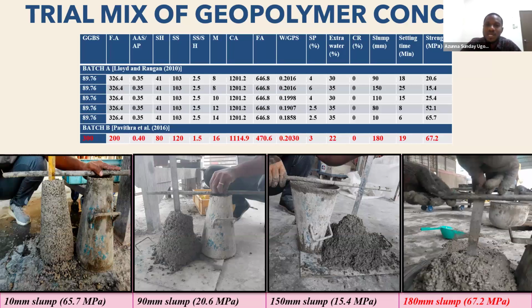The polycarboxylic-based superplasticizer is a no-no for geopolymer concrete. It has a high negative effect on geopolymer concrete. So the one that is a bit recommended is naphthalene-based superplasticizer because it's alkaline, and geopolymer is an alkaline concrete. So it promotes the alkalinity of the concrete.